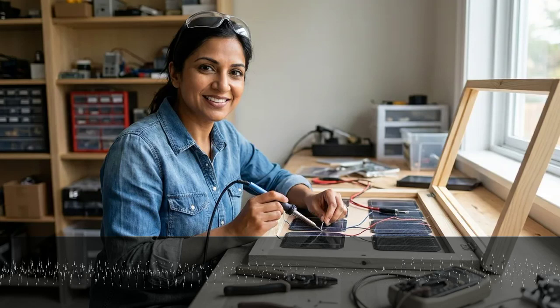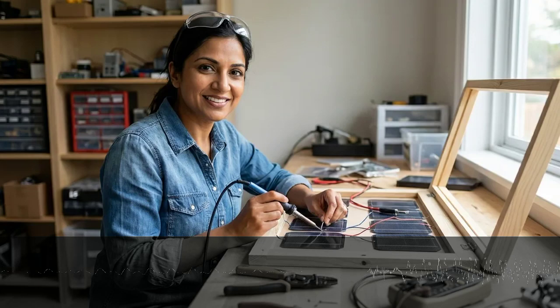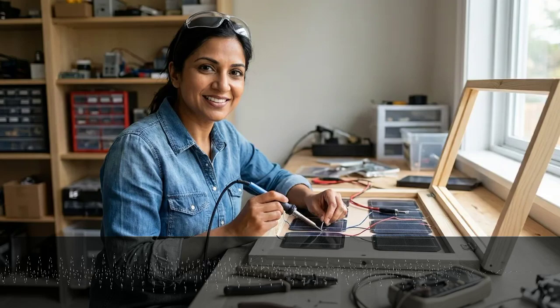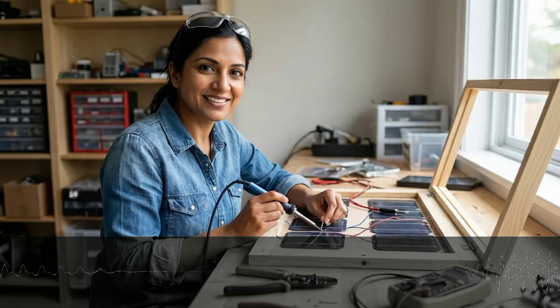How does aging affect performance? Measure your panel's output daily over 2 weeks. You should observe gradual decline as the cuprous oxide layer continues oxidizing or as the copper dissolves slightly into the electrolyte. This degradation mirrors real-world solar panel performance curves. Commercial panels lose approximately 0.5 to 1% efficiency per year, requiring replacement after 25 to 30 years.